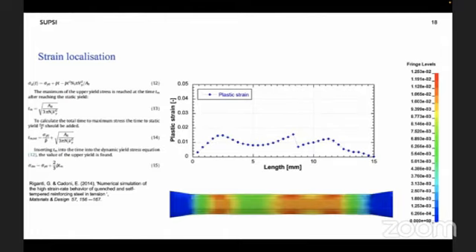A numerical simulation of dynamic tensile test was conducted using LS-Dyna to analyze both the distribution and the evolution of the plastic strain, as well as the dynamic neck formation. The specimen was modeled using the DAMP model, which takes yielding into account as a transient propagation of the shear waves from the initialization point. For this preliminary simulation, eight-node hexahedron solid elements were used, and a mesh size of 0.46 mm was used for the specimen and 0.92 mm for the bars.